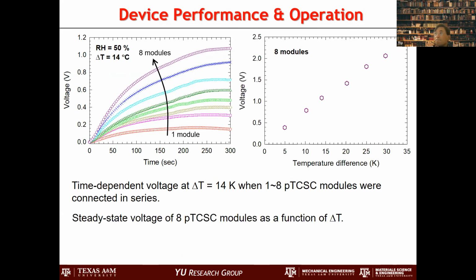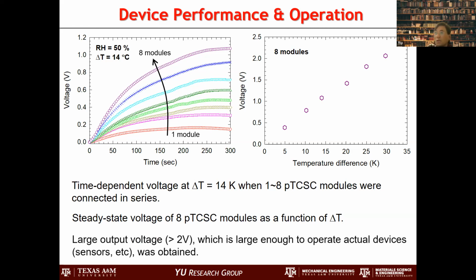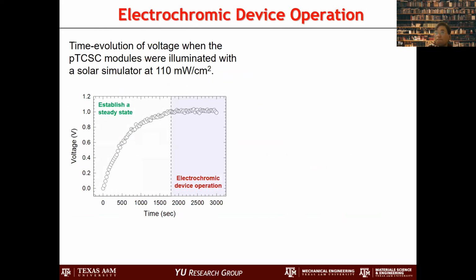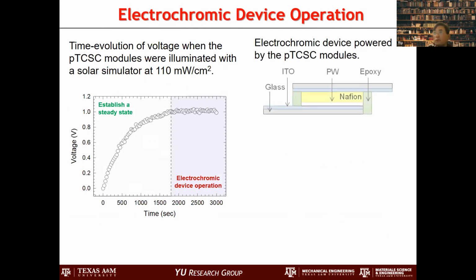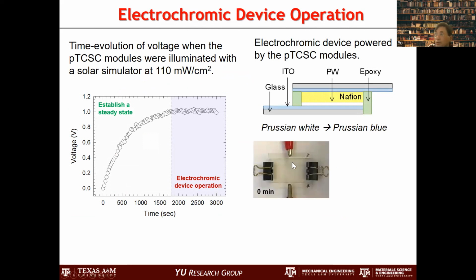On top of that, when we connect a module with a little bit larger temperature difference, we can actually have 2 volt, which is now in a range that we can operate a device without too much trouble. A typical device requires 1 or 2 volt, so small electronics. So this is something that we can do. So we actually tested whether we can use this as a power supply for some devices. We made an electrochromic device, which means that this device changes color when we supply electron.